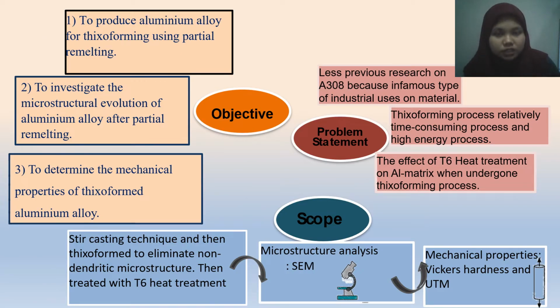There are three objectives for this project: firstly, to produce aluminium alloy for thixoforming using partial remelting; then to investigate the microstructural evolution of aluminium alloy after partial remelting; and next to determine the mechanical properties of thixoformed aluminium alloy. The scopes of this project are the stir casting technique, then thixoforming to obtain a non-dendritic microstructure, then T6 heat treatment, then microstructural analysis using a scanning electron microscope, and of course mechanical properties of the materials using Vickers hardness and a universal tensile machine.